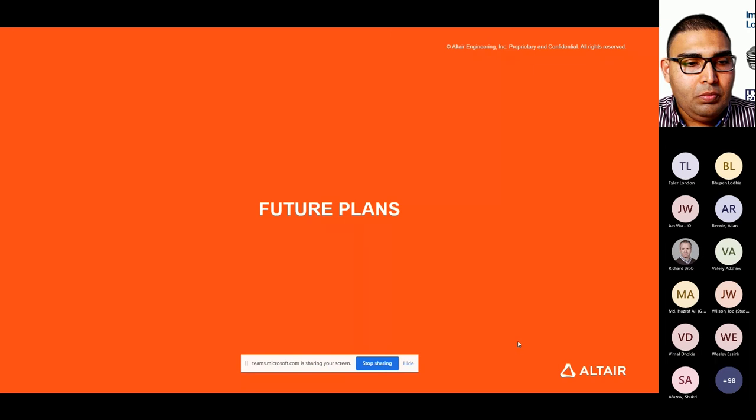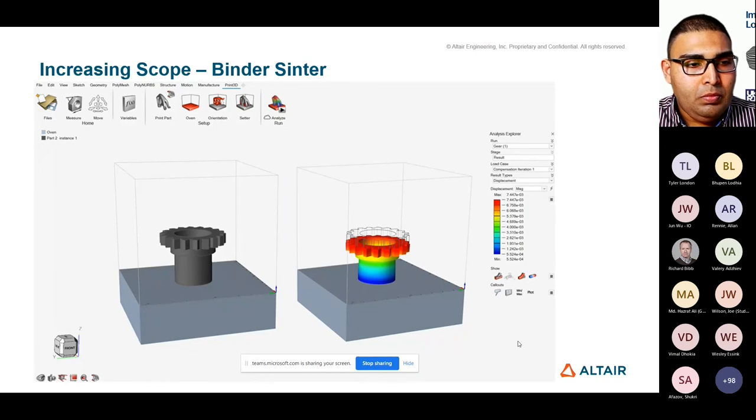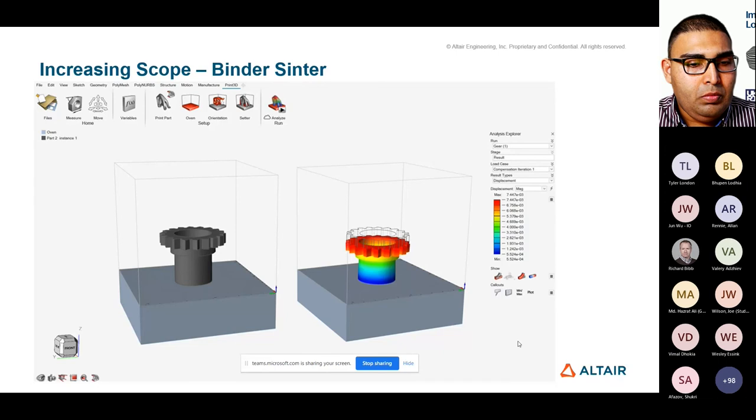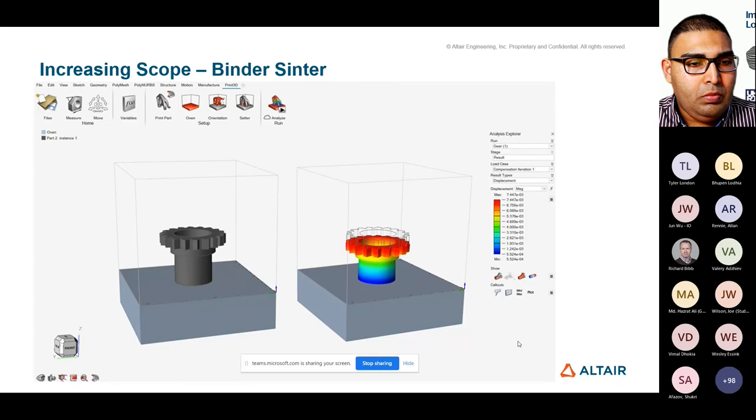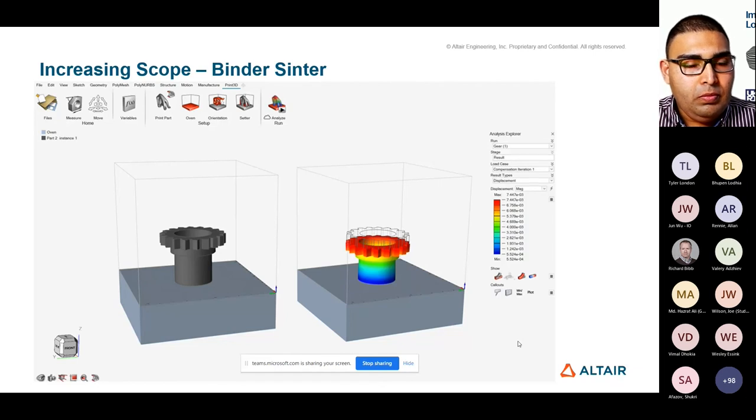So future plans. Where do we want to go? What's coming up soon? What are we thinking about? Very soon, next year, we are going to be introducing support for the binder-sinter method to additive manufacturing. So we recognize that binder-sinter in some applications is a very attractive approach to doing additive manufacturing. And so we have a workflow suited to that as well which is somewhat similar to what we've had for the laser powder bed fusion where we can pick up parts, we can define the parameters of our oven where the sintering is going to take place, we can set our orientation, and we can define the setters, the ceramic setters that are needed to support the structure during the sintering process.